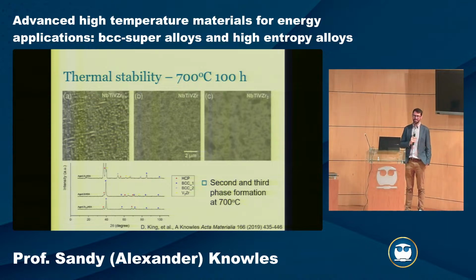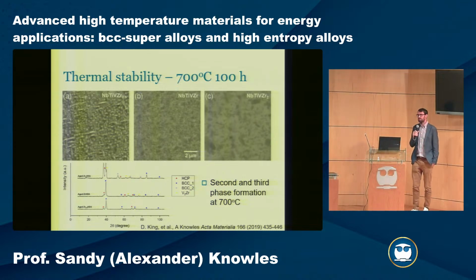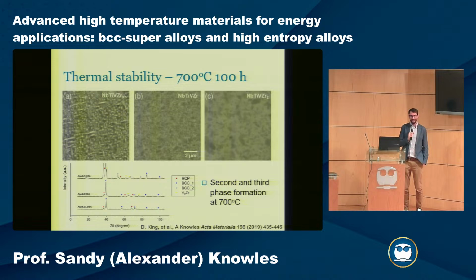My question is, what is the role of precipitation in refractory materials? Which one, sorry? The role of precipitation? Okay, yeah. So for us this is the key one. If you have just a simple BCC metal and you go to high temperature, you probably will get insufficient strength. So we need to add precipitates in order to get the high temperature strength as well as the potential creep resistance. That's where we do a lot of work trying to do this kind of phase diagram design to understand which phases and which precipitates might form, and at which temperature and which composition they form. And are the precipitates the intermetallic phase we really want? So yeah, that's a key question: how we design the specific precipitates. Thank you.